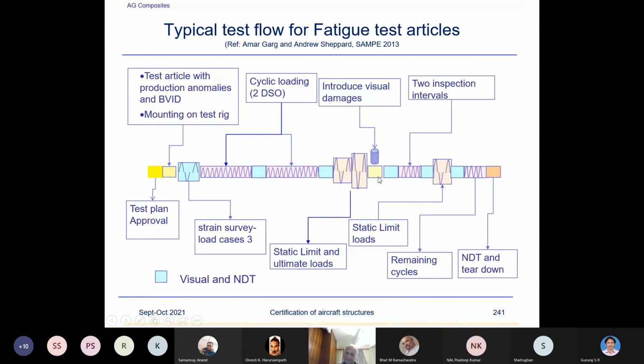Then we introduce the visual damages. Visual damage, slightly larger damage, like an impact using a 4-inch impactor, say, visible damage which is easily visible during walk around inspection. Then the requirement is to load it to 2 inspection intervals. Then of course, the requirement after this is to limit load.